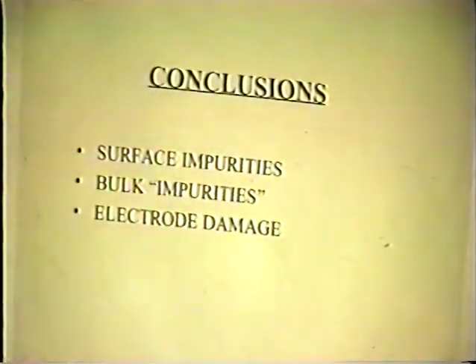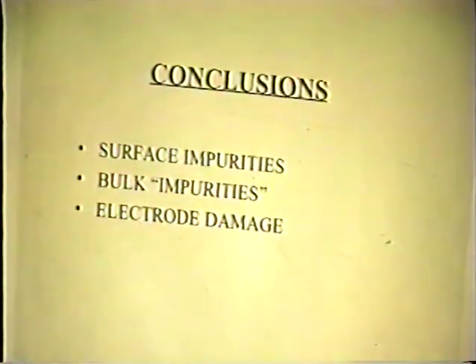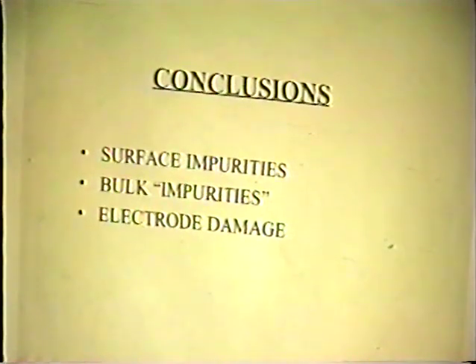that, first, we have observed by use of XPS surface impurities, what we call the first zone, which we can easily explain by electrochemical deposition of the element impurities from the solution where they exist. We observe a second zone of bulk impurities using energy dispersive spectroscopy, placed somewhere between 1 and 3 micrometers, for which we didn't have any good rationale to explain those results. And I have to say that electrode damage corresponds very much to the second zone, which we observed previously.